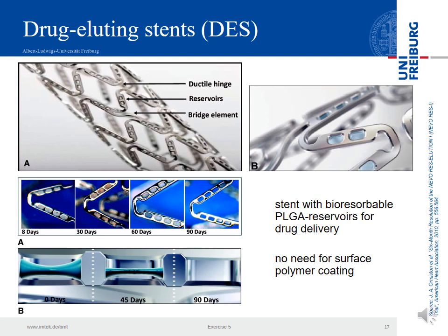Here's another design and a photo storyline to show that the drug is really released from the holes in the stent structure, and after 90 days nothing is left. And if you have those reservoirs, there is no need for surface polymer coating. You can put everything in those holes, in the reservoirs, and you get rid of that additional challenge that the polymer should stick to all surface structures.